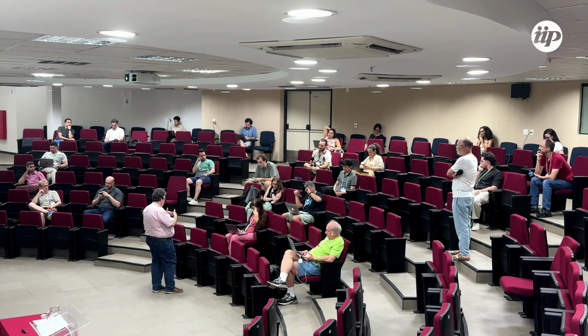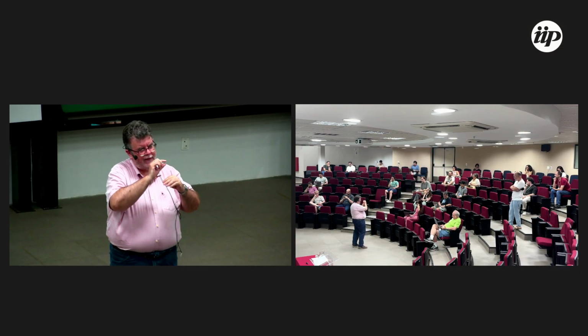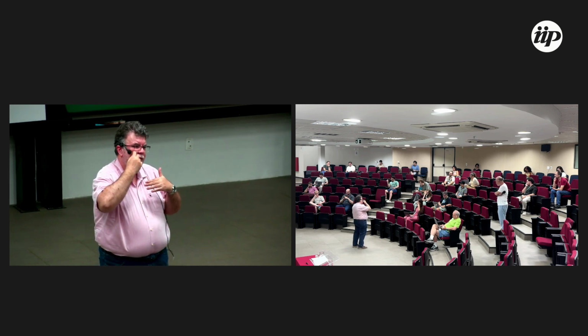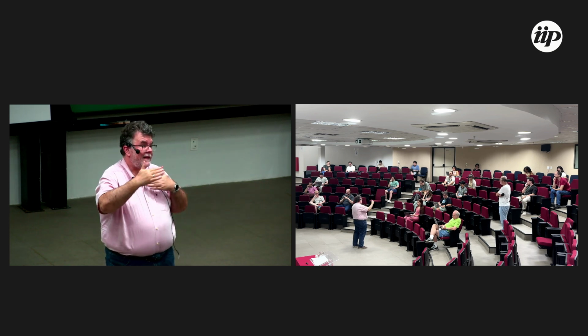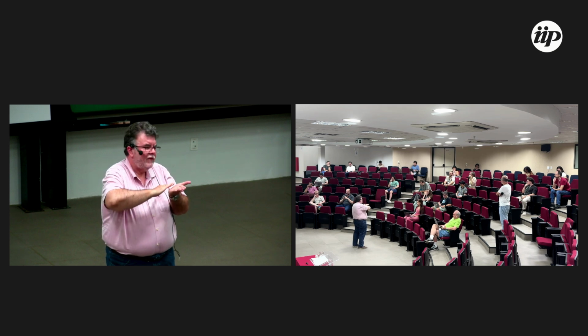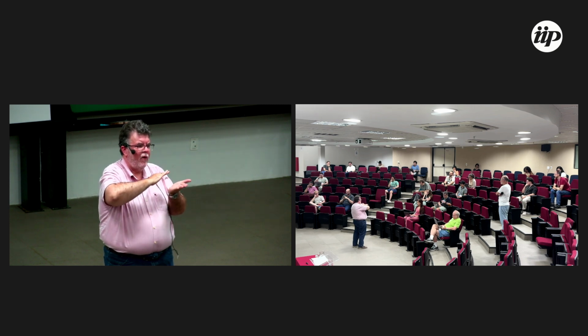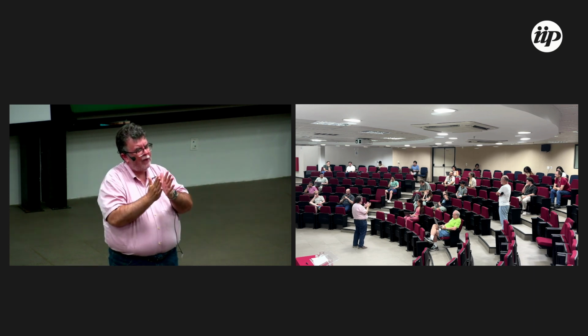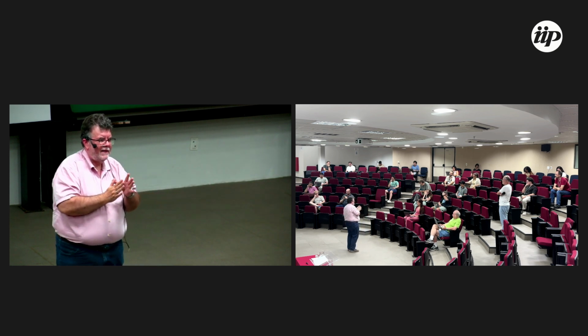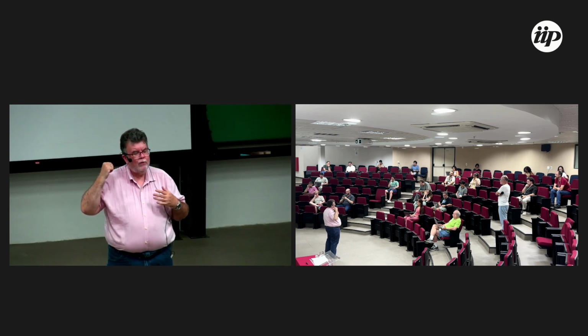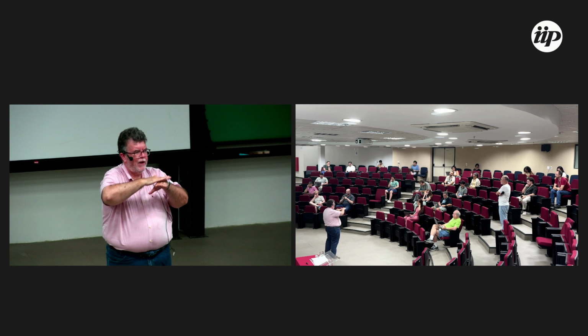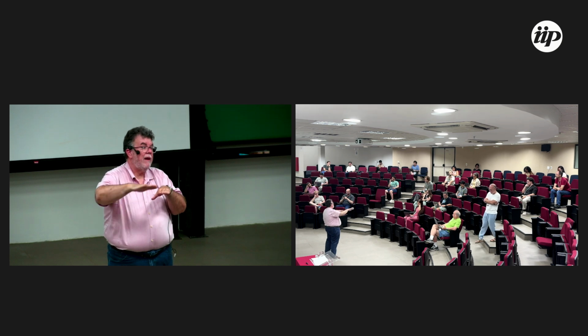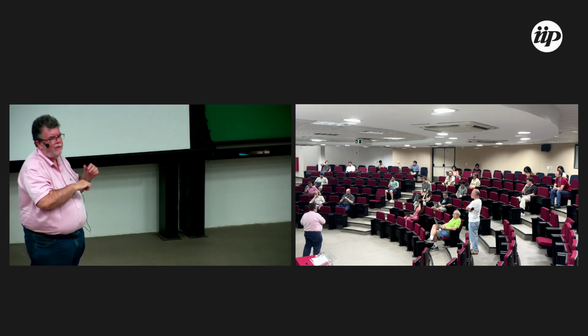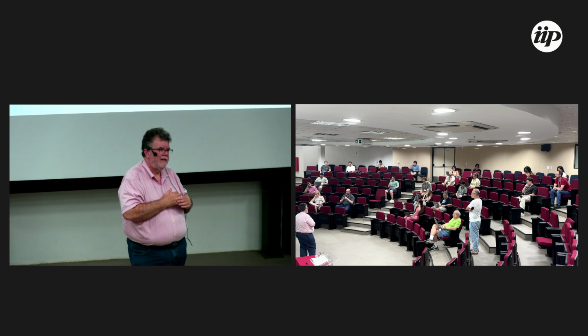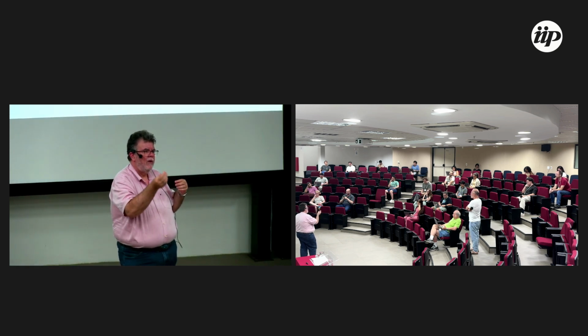Yeah, in thin films of chromium, for example, remember the size of the spin density wave is 6 nanometers, 60 angstrom. If you produce thin films of 10 angstrom, for example, or 20 angstrom, a reduction of the spin density wave is observed because of the reduced dimensionality of the system. Many works were performed by Zabel in Germany studying thin films, but not thin films of the alloys, because it is easier to produce chromium layer by chromium layer, vanadium layer by vanadium layer. It is not the same behavior, because the quantity of vanadium determines the response of the system. The idea of the impurity and the small effects.